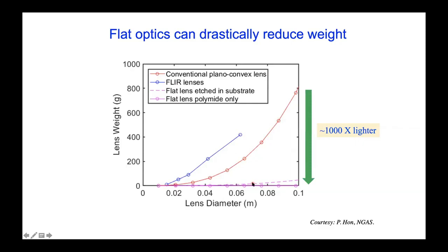And what we refer to as flat optics, as I'll explain shortly, can be directly etched into dielectric material like silicon, zinc sulfide, diamond, whatnot. Or they can be patterned into some polymer, like polyimide. We were interested primarily in polyimide because of the potential qualification in space. Even at a diameter of something like a tenth of a meter or so, we can potentially get an order of magnitude reduction of about 1000x or so. So it can have a pretty significant impact. This is the main reason we started looking into this.